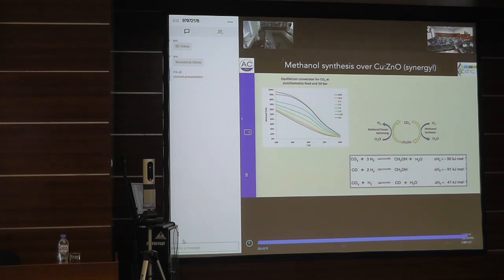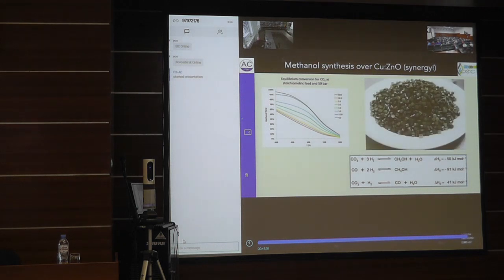That means you have to build plants that have an enormous recycling part in them, and the engineering design of methanol synthesis has to take care of this problem of recycling, because these are huge amounts of gas that you have to shuffle around at 50 bar pressure. Nevertheless, that exists. This is an industrial version of a catalyst. Our department was severely involved in the recipe formation of making this catalyst. This is a pretty good state-of-the-art material that produces at 50 bar pressure, as benchmark information, about 1.5 kilograms of methanol per kilogram catalyst an hour. So this is the ballpark in which that works.